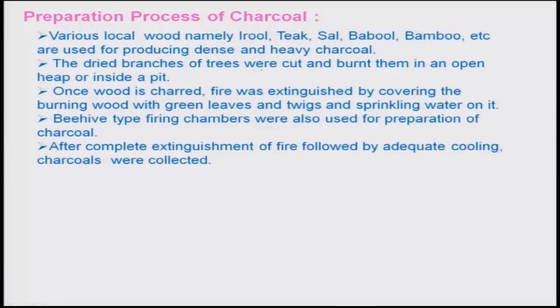Dense and heavy charcoal was needed for this kind of work. The ancient people were aware of which wood would give the best results and always relied on local materials. The dried branches of trees were cut and burnt in an open heap or inside a pit, such that pyrolysis would occur, gases would go out, and carbon would remain. Once wood was charred, fire was extinguished by covering the burning with green leaves or twigs or sprinkling water on it.